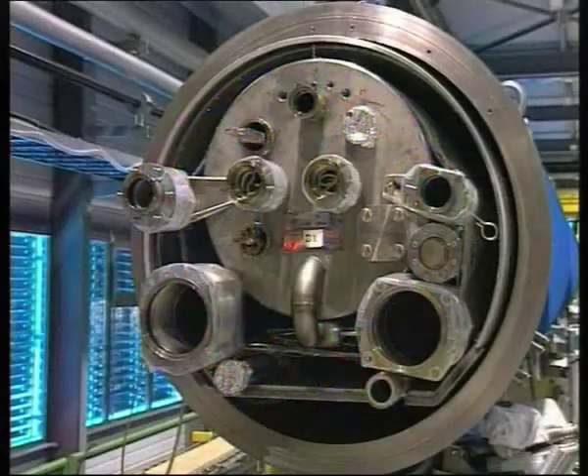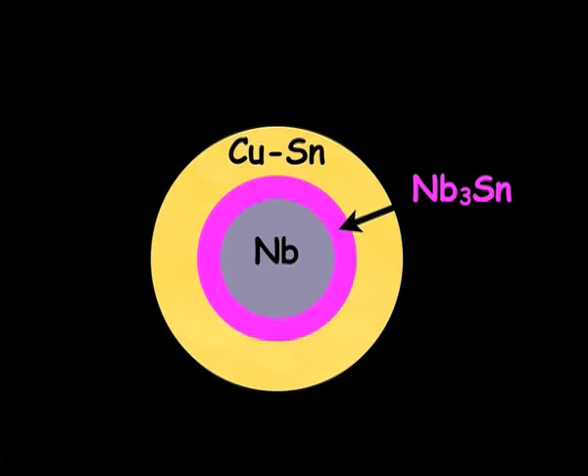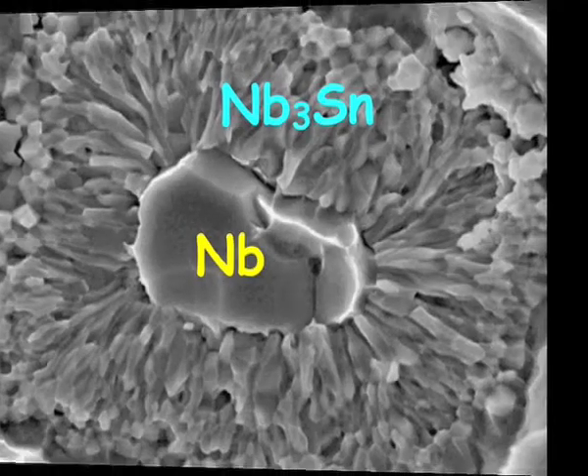You have to heat treat the coils that are wound. So after you have made the coils, you have to heat treat them at 700 degrees, so that's very difficult from an engineering point of view. And again, if you increase the field and the current density, of course, in the coils, then the Lorentz forces also will increase dramatically with the field.